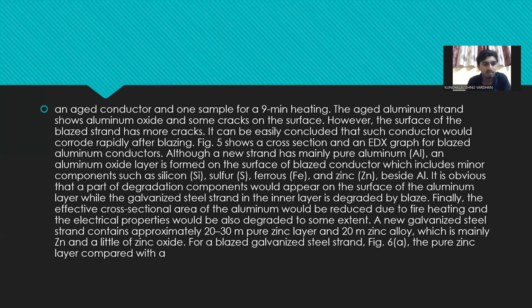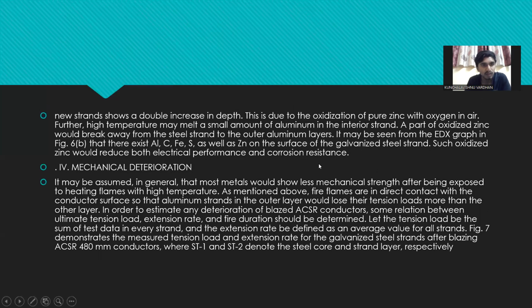A new galvanized steel strand consists of approximately 20 to 30 pure zinc layer and the 20 zinc alloy, which is mainly Zn and a little of zinc oxide. For a blazed galvanized strand, the pure zinc layer compared with a new strand shows a double increase in the depth. This is due to oxidation of pure zinc with oxygen in air. Further, high temperature may melt a small amount of aluminum in the interior strand. A part of oxidized zinc would break away from the steel strand to the outer aluminum layer.